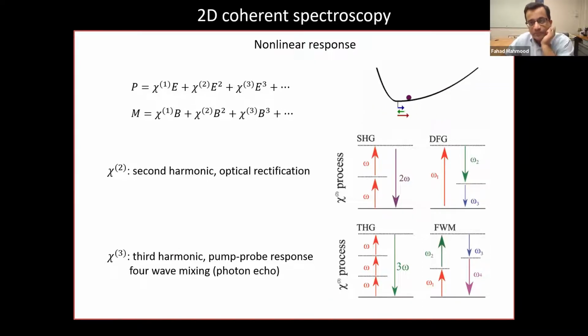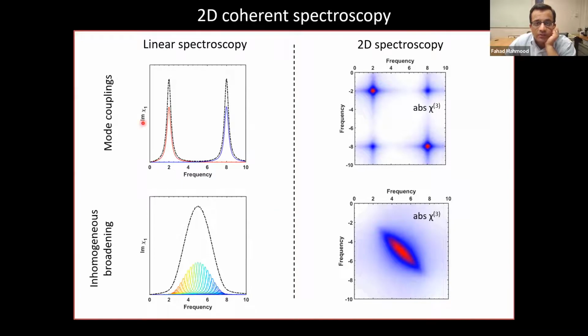Okay. So again, going back to this comparison between our 1D spectroscopy and 2D spectroscopy. In the 1D case, we plot susceptibility with frequency. In the 2D case, there are two different frequency scales. And so we can look at couplings between different modes. We can distinguish between inhomogeneous broadening and homogeneous broadening, which is very difficult to do when I'm doing linear spectroscopy. Okay. So we're going to try to do all of this in the terahertz range.